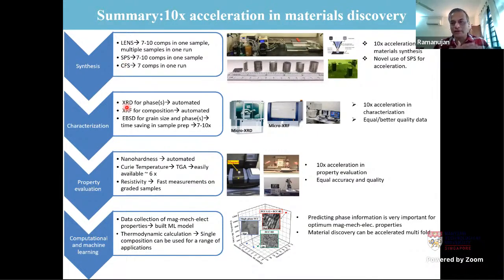Then we use automated XRD, which can scan several samples at a given time. We use XRF and EBSD. Of course, there's always room for improvement in these things as tools come online. And then we use nano hardness, which is automated. And for Curie temperature, as I said, we've developed our own system using TGA for rapid analysis of the Curie temperature, and get the resistivity values. And then we use AI and machine learning tools in conjunction with these experimental tools to build models. And we can also add thermodynamics to this to further enhance the accuracy of our models.